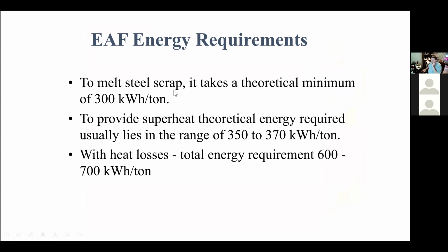To melt steel scrap, it takes a theoretical minimum of about 300 kilowatt hours per short ton. And then you provide superheat, because you don't want to tap the steel from the EAF at its liquidus temperature, because as soon as it chills a little bit, it'll start to solidify. So we have to provide a sufficient amount of superheat to keep it liquid so that we can continue to process it and then get it to the caster.